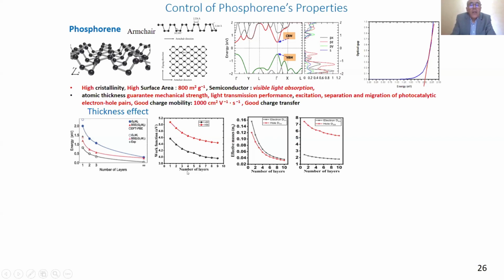And this thickness also changes the work function. This is useful for the charge transfer, and also changes the effective mass for holes and electrons in both directions, armchair and zigzag. And this is responsible for the mobility. As I said before, the mobility is higher for holes in the armchair direction, and we can control this mobility by increasing the number of layers. This is the first effect to change the properties of phosphorene.